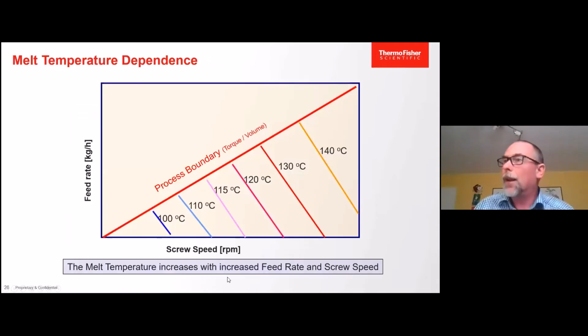When we talk about melt temperature, what we can see is there is always a process boundary. We call it a feed rate and screw speed diagram, where we can see this process boundary. Either it is determined by the volume, so that means you cannot bring enough material somewhere, there is a limit to push material into this extrusion system because it's a smaller lab scale.